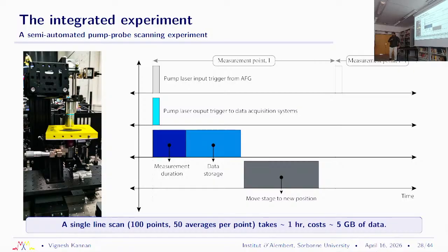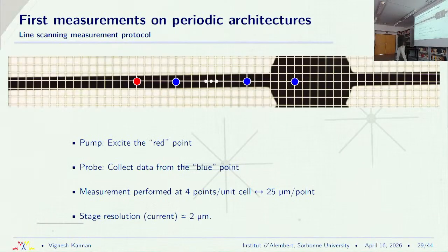And that's a lot of data. So we will soon hit limits of how we save and analyze this data rather than actually getting a large data set, but we're not at that stage just yet. So our first measurement was on the square unit cell, because we needed to check if our fabrication technique works and if we can actually pick up the dispersion that we got from our large scale system.